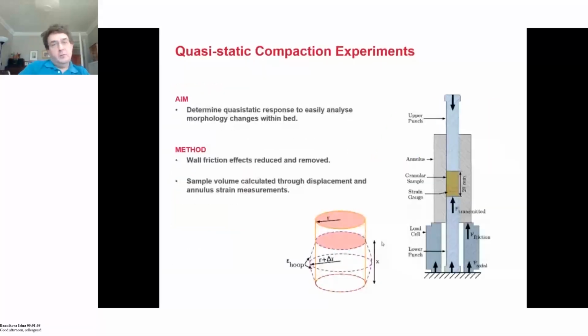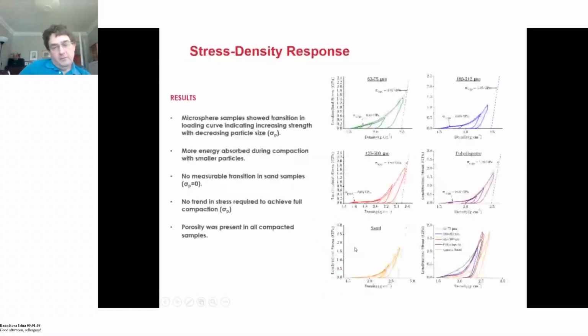Now, we started initially doing some quasi-static compaction experiments, and there are a number of ways of doing this. But what we particularly did was mount a system where we could measure the force applied along the direction of loading to the sand, but also, by having a collar with an instrumented load cell down below, we could measure the force being transmitted to the outer side of the loading chamber. So effectively, we're removing the effects of wall friction from the system or reducing them very significantly. We can also know about the mechanical properties of this jacket. Again, we can measure the strain on that jacket as well. So we can get a good measure of the components of loading of the system.